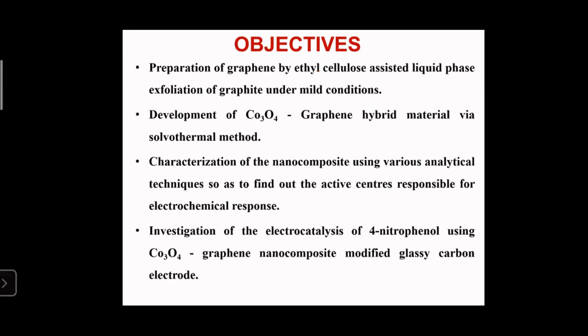So the objectives are the preparation of graphene by ethyl cellulose assisted liquid phase exfoliation of graphite under mild conditions. We are using a bath sonicator for the exfoliation of graphite. And here we present the composite of cobalt oxide with graphene, prepared by the solvothermal method. The material is characterized using a few techniques just to find out the active centers responsible for the electrochemical activity. We also investigated the electrocatalysis of 4-nitrophenol using the produced cobalt oxide graphene nanocomposite modified glassy carbon electrode.